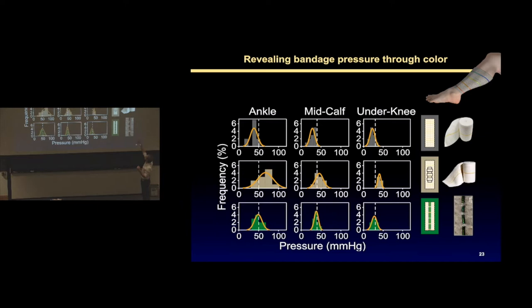And you can see that our bandage, the fiber in the bandage is designed such that we show this fiber being yellow in a good range. And then it gets blue when it's too high. So we didn't get it to go from blue to green to red. Red being the only color. We go from red to green to blue. Because this textile gets thinner and it's shifted the colors. You can engineer it to do a different thing, but we were sufficiently happy with this so far. And my students went and did this. This is just a model. But they were using these bandages on each other and other people that were volunteering. Anybody who was willing enough to come in and be wrapped, got wrapped. With these bandages and try to see if we can improve the amount of pressure sensitivity we get and the amount of pressure reliability as we applied. You can see the three different bandages from here that we tested. One that has no markings whatsoever, just this midline. One that has rectangles. And you have to stretch these rectangles to be squares and then apply them. And that's the only pressure sensitivity that you have. And then we used our fibers. And through these fibers, we added a color chart. The color chart would show you its color corresponding to a certain pressure. And so if you want to get 4.6 kilopascals, you would look at this color and then try to adjust this color on the fiber.